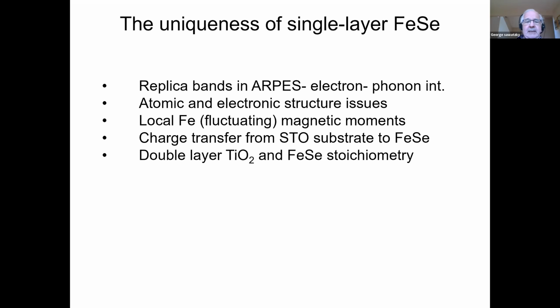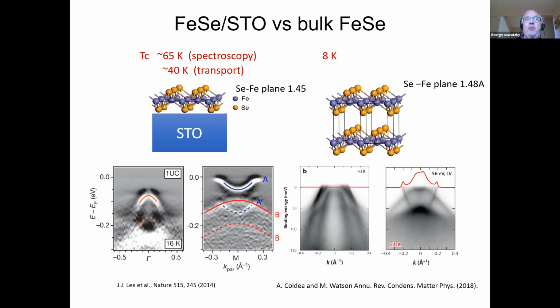You know, we all have problems with what actually the structure is, what actually the chemical composition is. Even in the case of iron selenide, one claims from Cava's work that the line phase, the real line phase is something like 1.01 iron selenium. Okay, so there's extra iron in there of a very typical, very small amount, which gets me to think about, you know, your very low concentrations of manganese, for example, that really affect the superconductivity and the behavior of your 111 crystals, which you, of course, have very nice crystals.